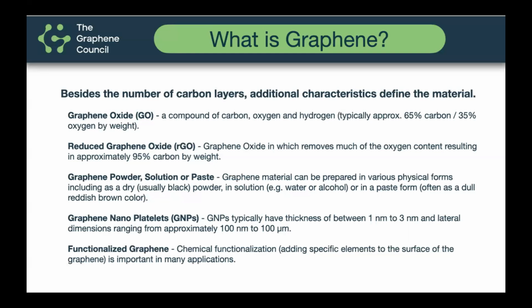Graphene can also be produced and delivered in the form of a dry powder. It can be in a solution, or it could be in a paste format. Those also have implications on how you can use graphene or apply it to your application. And then we also have a category of materials called functionalized graphene, which have been intentionally altered with chemicals on the surface or the edges of the graphene flakes for different reasons. For example, it might have a surfactant added to it to improve its dispersibility in your host matrix. When you take all of this together, the different chemical combinations, the particle morphology, the layer count, we end up with hundreds of iterations of graphene material that is in the same family, but does behave differently depending on the application that you're looking for.